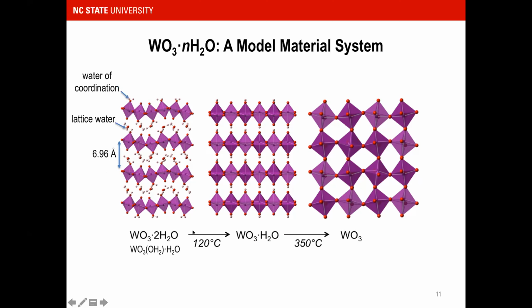If you heat this material up just at a low temperature, that lattice water is removed and you form the monohydrate structure. The water of coordination remains, and it's a little hidden here, that second hydrogen back here. At a much higher temperature, you can completely dehydrate the structure.